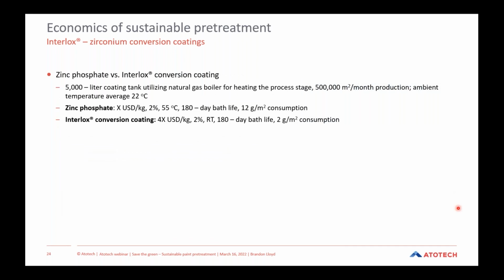So if we move into the example of an applicator considering a conversion from a zinc phosphate to our Interlox zirconium-based pretreatments. Again, very similar scenario here, 5,000 liter operating tank with 500,000 square meter production. If we look at the zinc phosphate process, typically we'll have a cost of X US dollars, operating at 2%, 55 degrees Celsius operation, and 180-day bath life. Here, the big difference being the chemical consumption of 12 gram per square meter. This is quite common of a phosphate-based pretreatment.